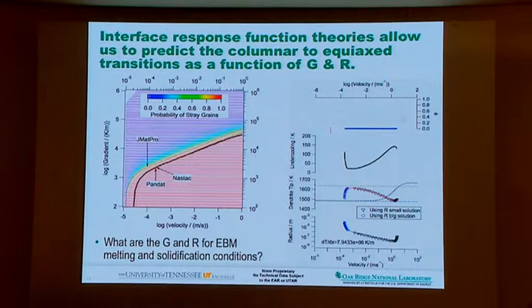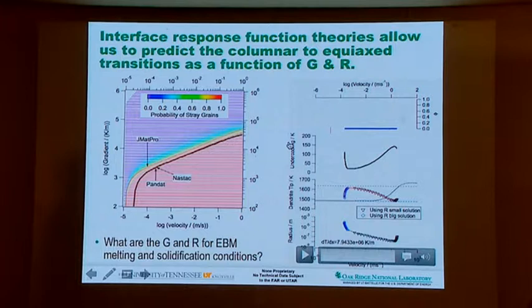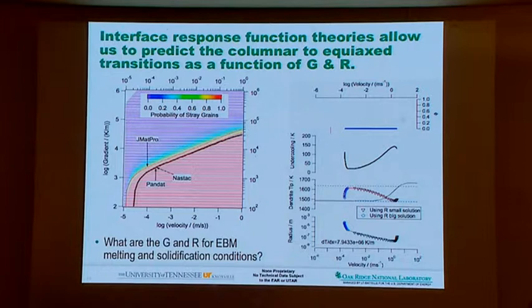You can use those theories and tell under which conditions you will get columnar growth and under which you will get equiaxed growth. So it's good, we have a diagram. I hope you saw the video run by, to show that I'm not lying. I actually did these calculations. You can see that if you are over here, you'll get columnar. If you are here, you'll get an equiaxed structure. If you understand the heat transfer in steady-state welding, that is hard to do, because there are a few orders of magnitude variation in thermal gradient and liquid-solid interface velocity. What do we do about it? This is an issue.